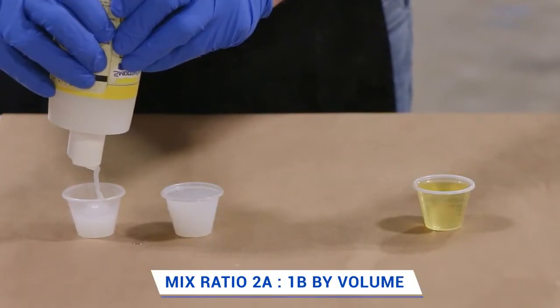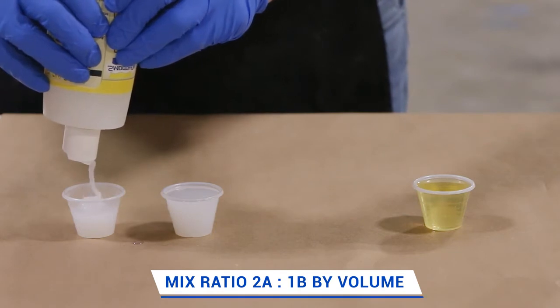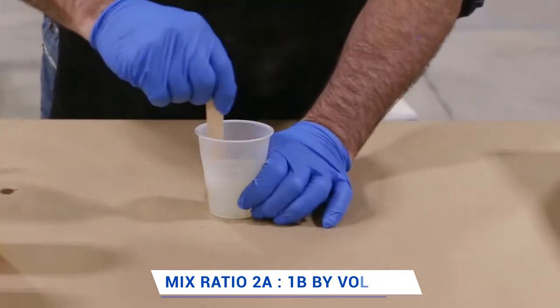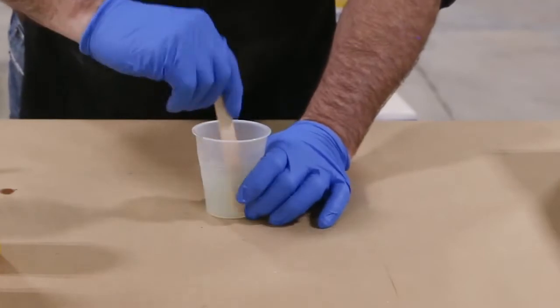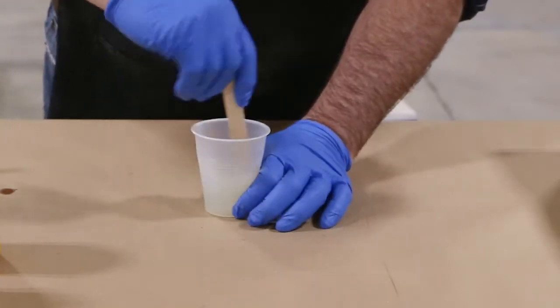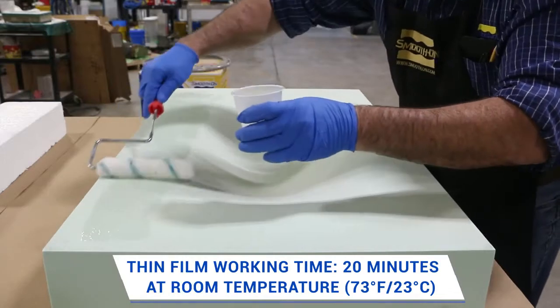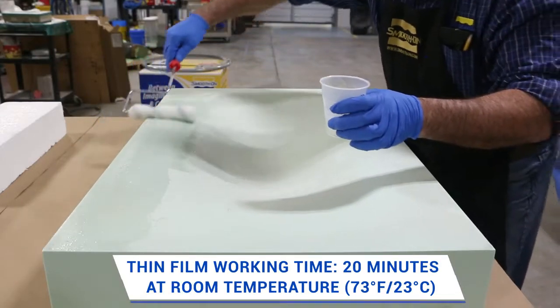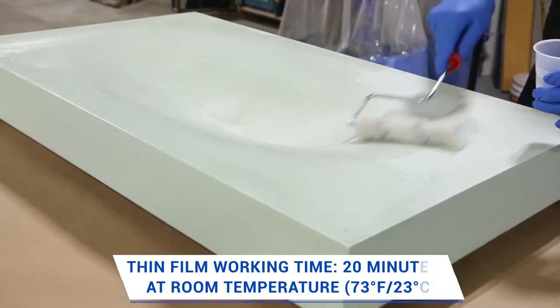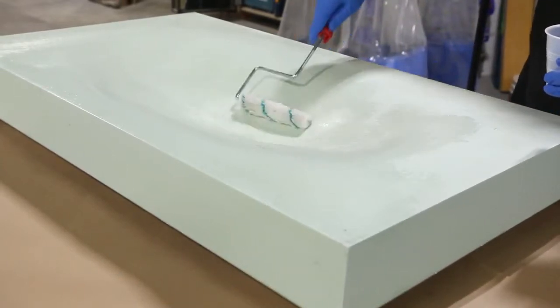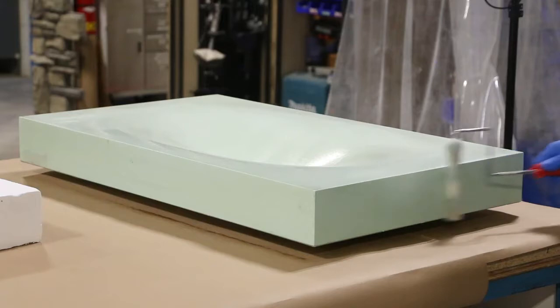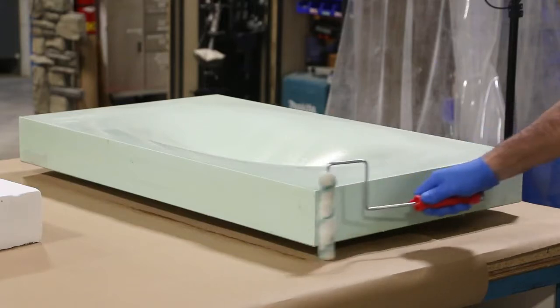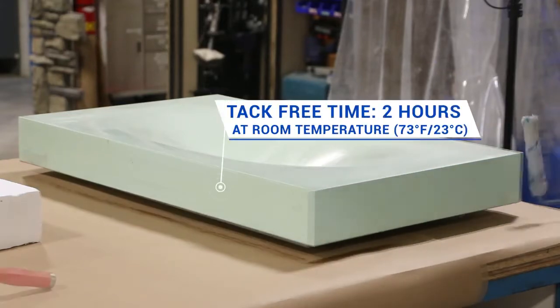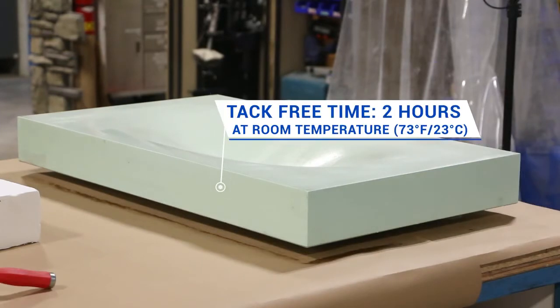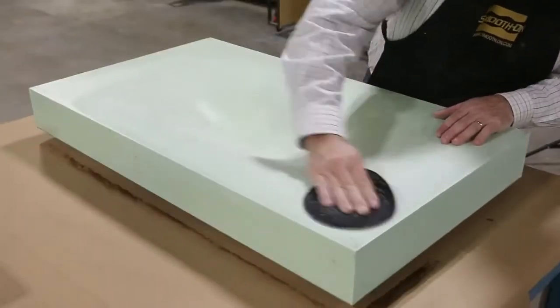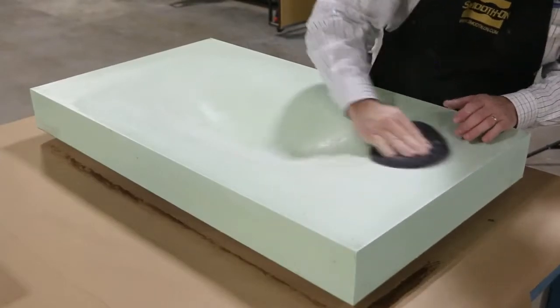I then dispensed XTC-3D to be used to coat the top surface of the model. The goal is to apply the thinnest possible coating while making the surface hard enough to be sanded without losing the original profile. Pour and spread the material with a roller until all surfaces are covered. Allow to cure until tack-free. Once tack-free, you will be able to sand by hand in order to inspect the model for uniformity.